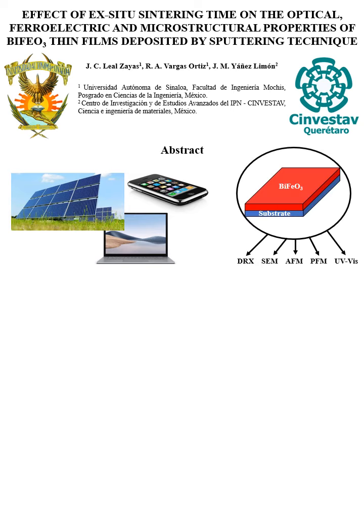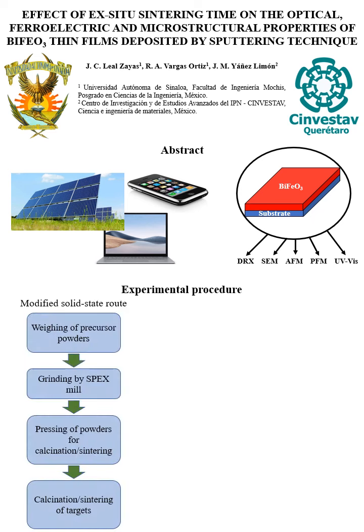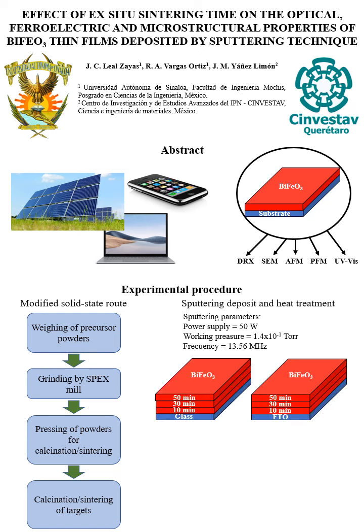In this research, we deposited thin films of bismuth ferrite onto two different substrates and evaluated its structural, optical, and ferroelectric behavior. The targets we used in the deposit process were obtained by a modified solid-state route, and the deposit process was carried out by sputtering.